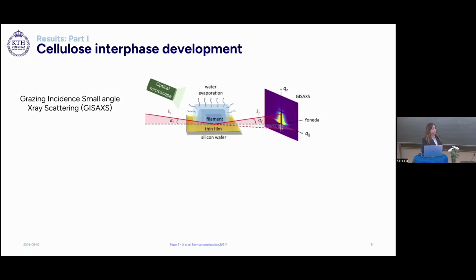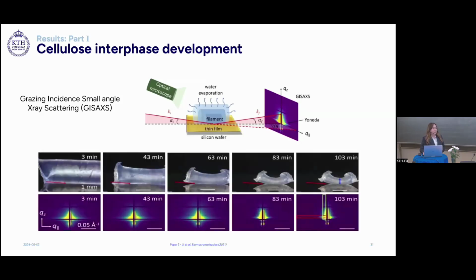However, instead of dropwise precipitation, we used a continuous flow to create the filaments. And the GISAXS measurement was performed by placing the wet filament on the cellulose thin film spin-coated on a silicon wafer and allowing them to dry while exposing the interfacial area to a micrometer-sized beam. 2D patterns were obtained and analyzed by performing horizontal and vertical integrations on the Yoneda peak, which is the area where we have the strongest scattering. And the dimensions of the filaments were monitored using an optical microscope.